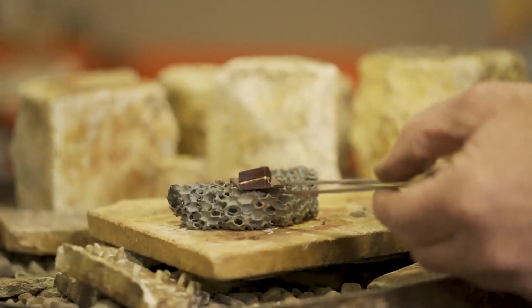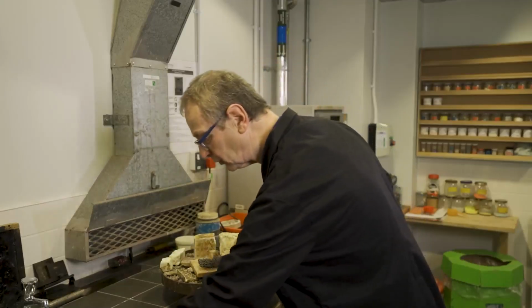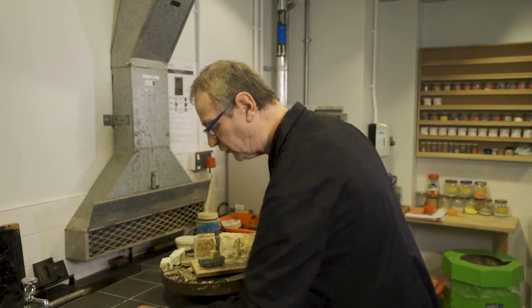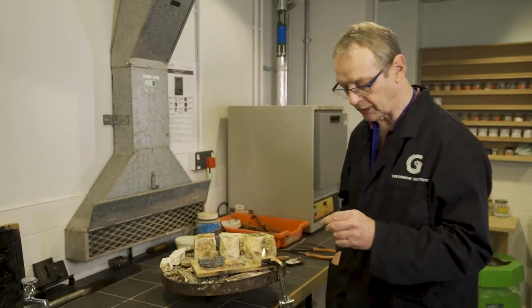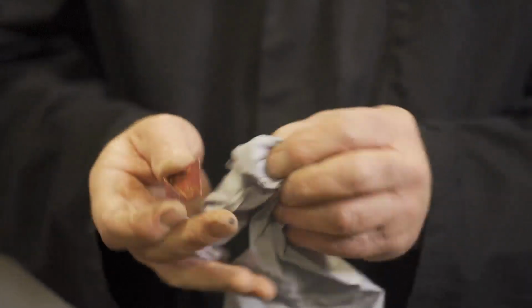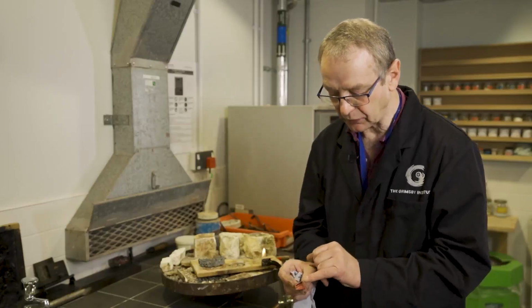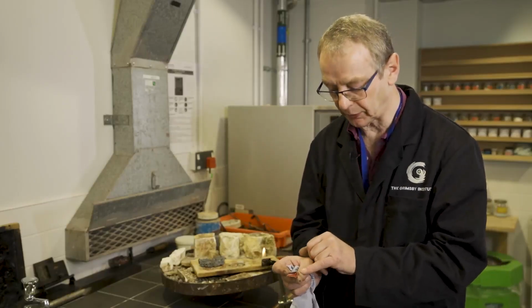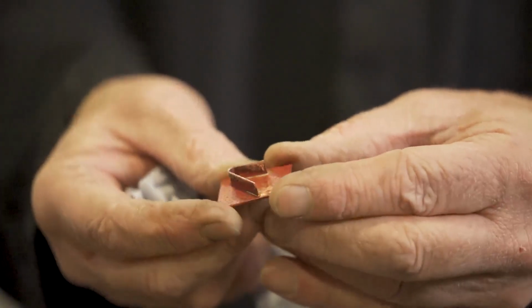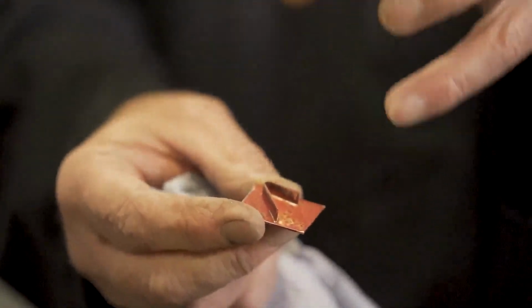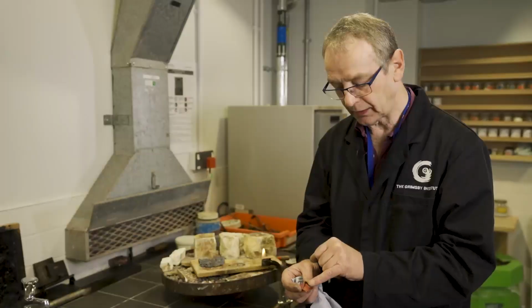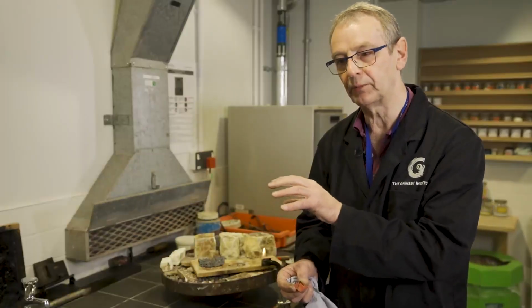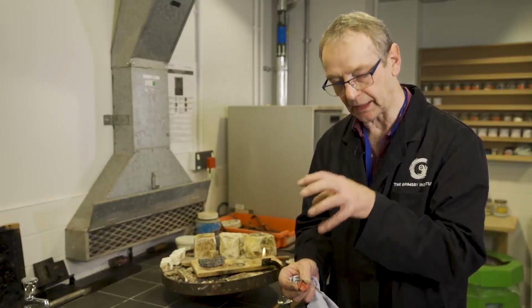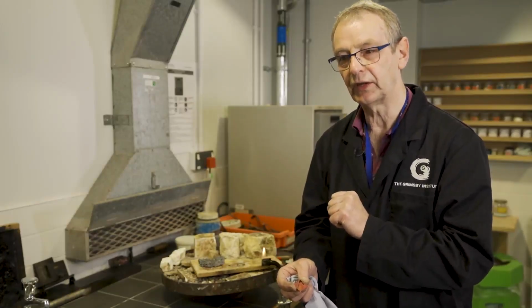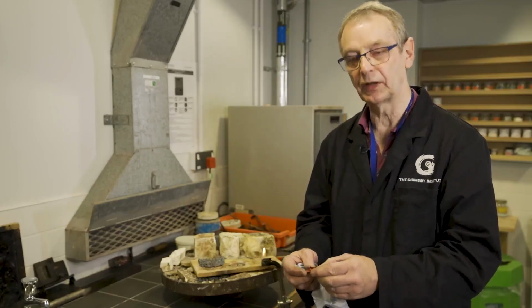So once it's cooled down a little bit, then just quench it straight away in the water, and we can see that the solder's run all the way round on the inside, and because we've got the heat perfectly right, and you can see this sort of glassy coating the borax has left, and that's protected the metal. And if we wanted to get rid of that, then we could put it into the pickle, and the acid would eat into the flux and clean all the metal up.